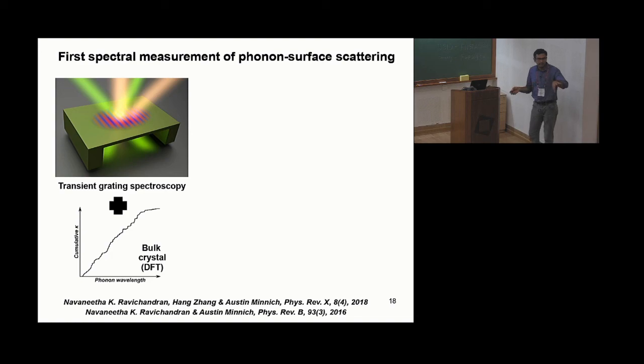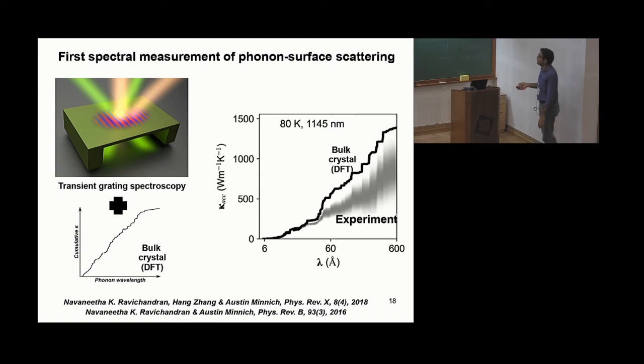So we have this grating period dependent thermal conductivity, and by combining it with what we know about intrinsic scattering mechanisms, we are now able to extract the accumulation function for thermal conductivity for this membrane in the presence of boundaries. This black line is theoretical calculation of how thermal conductivity is distributed among different phonons, and this gray curve is what is happening in the membrane itself in the presence of boundary scattering.